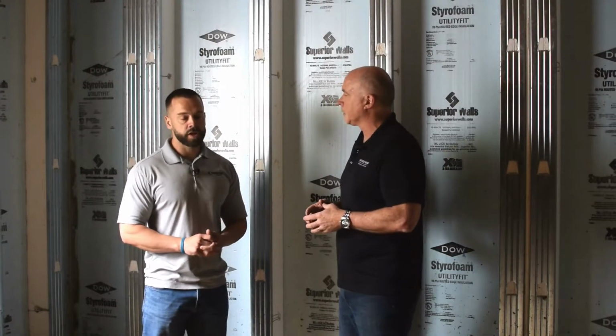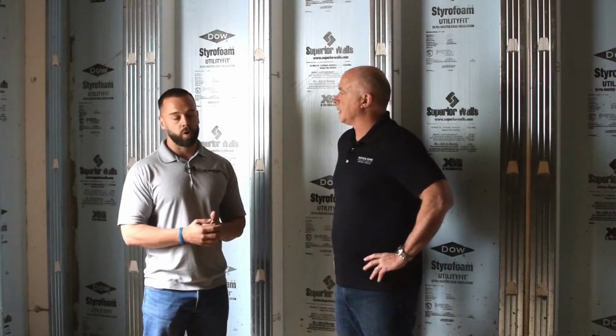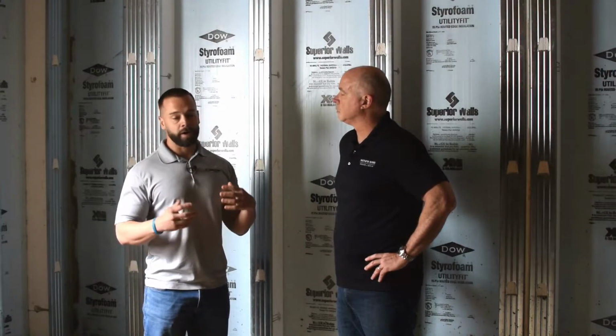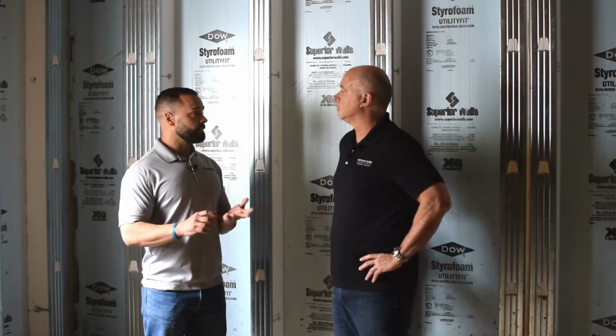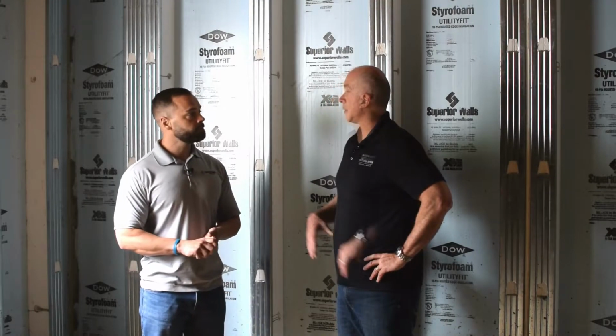Is that correct? Correct. So working within a climate controlled facility allows us to control the mix of the concrete. So all the walls are made customized to each particular build. Every wall is a little bit different. It's engineered a little bit differently depending on what the specifications of every house are. With our walls, we test the concrete after every 7 days, to make sure that it holds at least a 5,000 PSI crush test. Right, so that's compared to a 3,000 PSI mix, so it's substantially stronger. And that mix and that density gets us a waterproof concrete, which a standard field pour does not reach.